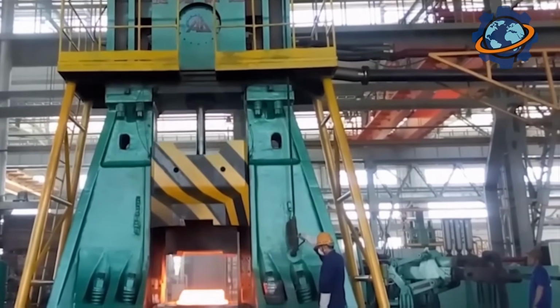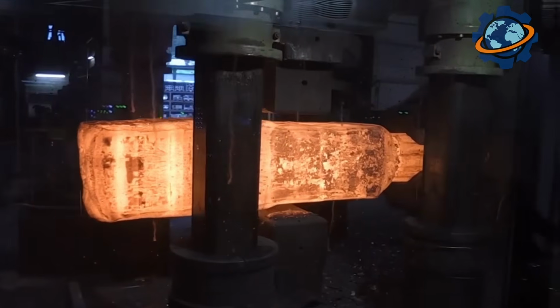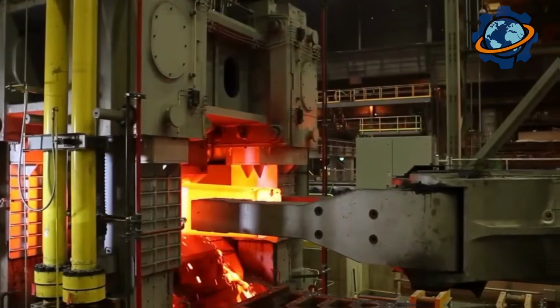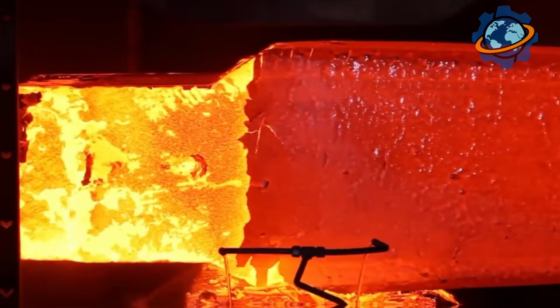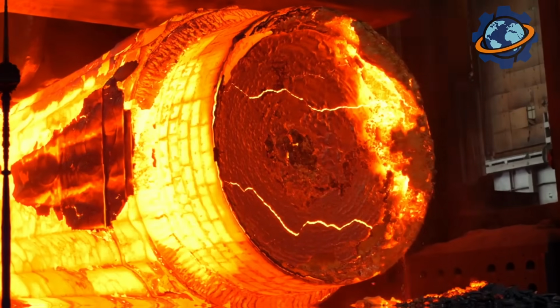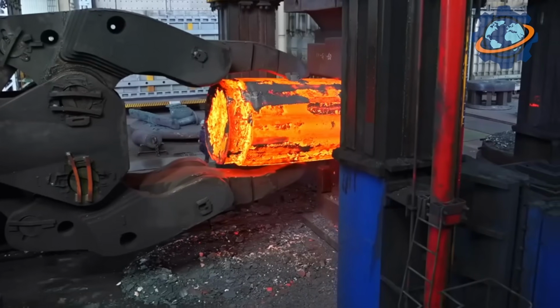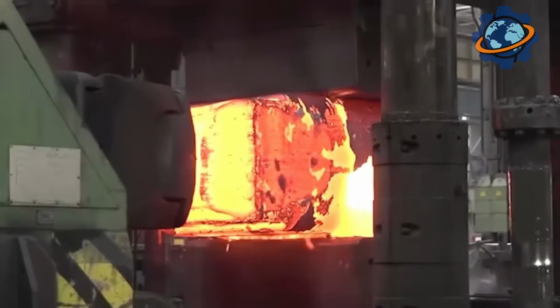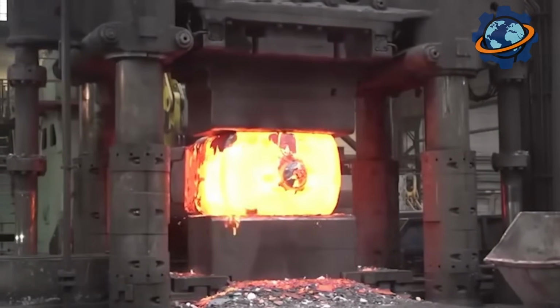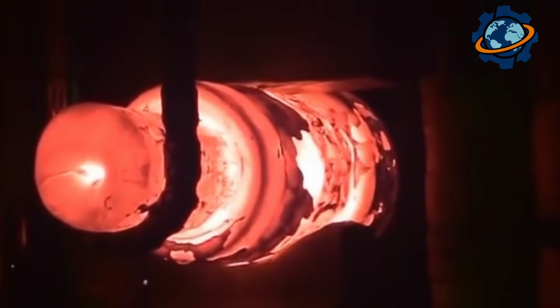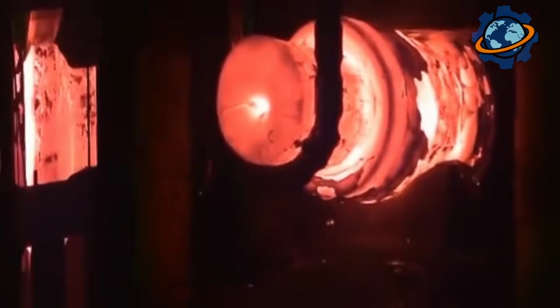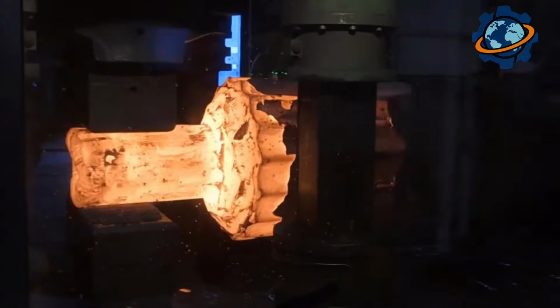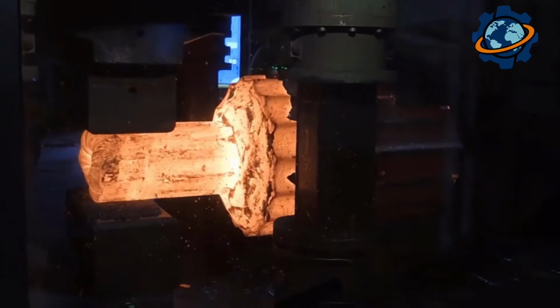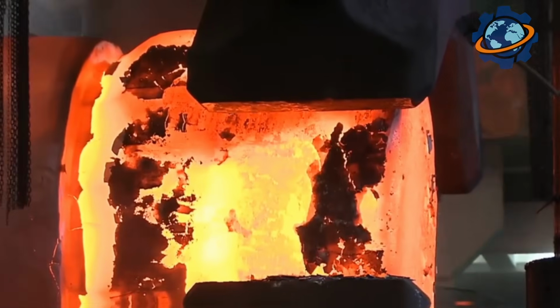From the start, the press drops and hammers the ingot with 15,000 tons of force. The sound is so loud that even through earplugs I feel the vibration in my chest. The ground beneath my feet shakes. The ingot flattens slightly, maybe 2 inches per strike. But this isn't just brute force. Every blow has to be precisely calculated. Hit too hard in one spot, the metal can crack. Too soft, the structure won't compress.